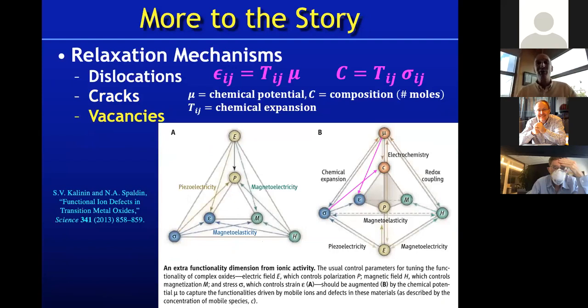Now another important reality is another way, other than relaxing through dislocations or cracking, in which the system can accommodate the different size substrate that you presented it with. One way that it could accommodate that is it could form some defects, and those defects cost energy, but maybe those defects are ones that make it so that the material matches better to the substrate, and you get a payoff in all that elastic strain energy that you can put into the defect energy. Now, to explain this,